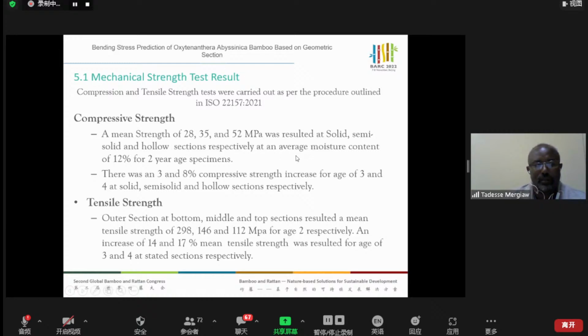solid, and hollow sections respectively, with an average moisture of 12% for 2 year age specimens, and there was a 3 and 8% increase in compressive strengths for the ages of 3 and 4, with the same moisture content. And the tensile test is done with a dog bone shape based on the outer sections. Tensile strengths of 298, 146, and 112 megapascals for age 2 respectively resulted, and the result increased. A 14 and 17% mean tensile strength increase resulted for the ages of 3 and 4 at the stated sections.